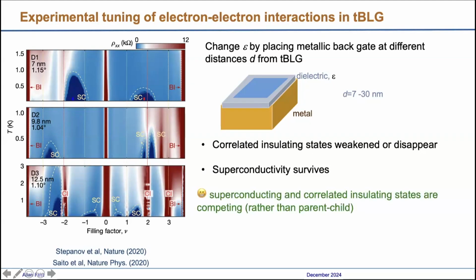From these, what they conclude is that the correlated insulating state and superconductivity are competing rather than parent-child. For example, there was some thought that maybe the superconductivity is obtained by doping the correlated insulating state. So the conclusion is that they are competing states. I think they are actually very careful in reaching that conclusion. But if you want to take one step further, as some of the theory has done, you might take this as evidence of superconductivity being independent of electronic interactions.